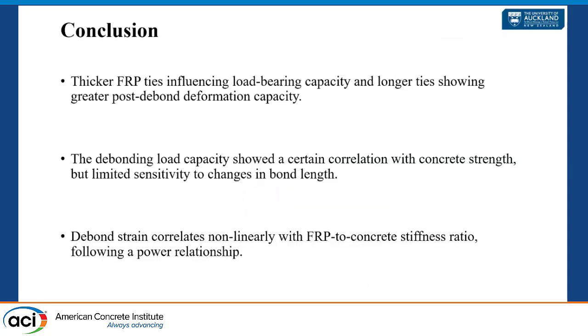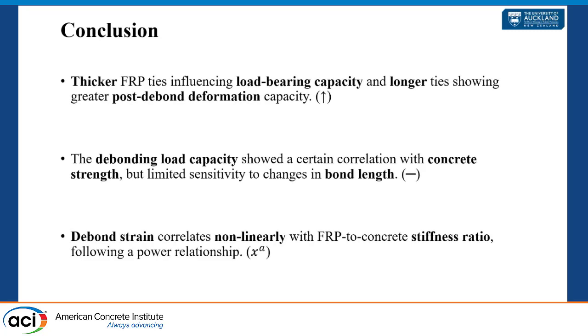Okay, here are some conclusions for takeaway, primarily from three different aspects. The first aspect is the size effect. We found that thicker ties always have a higher load carrying capacity, and the longer ties have greater post-debonding deformations.